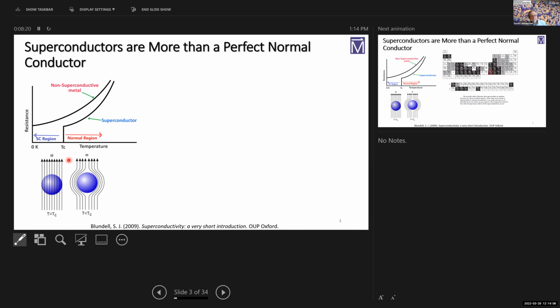But in the mid-1930s, Meissner and Ochsenfeld started playing around placing superconductors in magnetic fields and realized that there was a second independent property. Whereas in the normal state magnetic flux just penetrates pretty uniformly, according to standard paramagnetic or diamagnetic behavior, once you went into the superconducting state, you got a very strong distortion of the magnetic field around the superconductor, because the superconductor, and they were working with pure metals, completely excluded the flux.